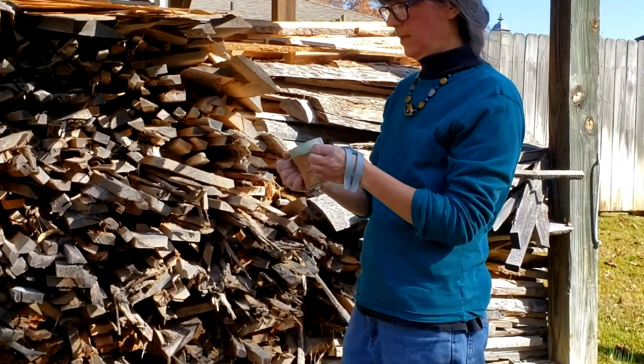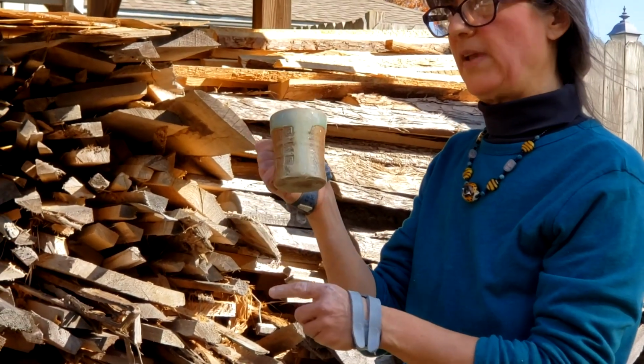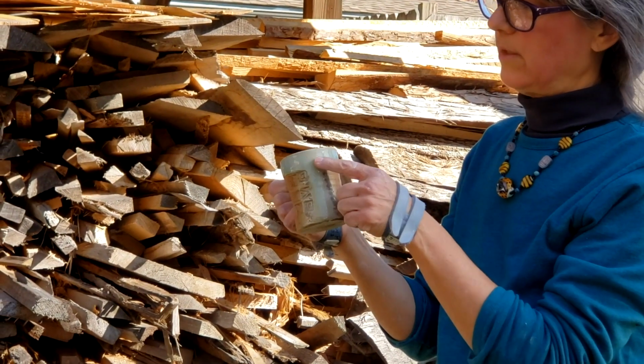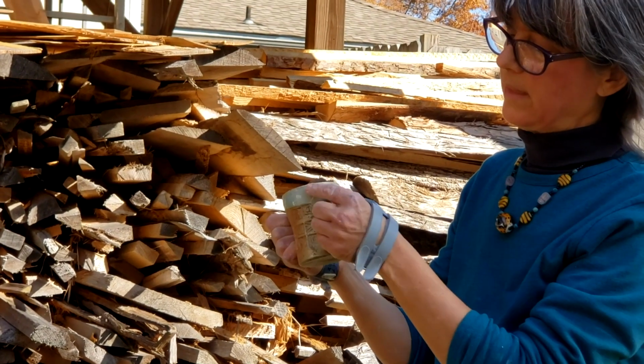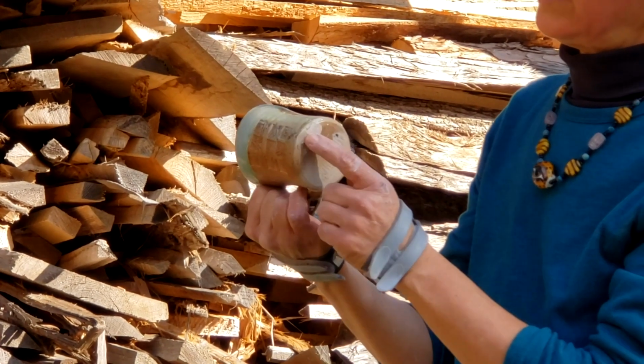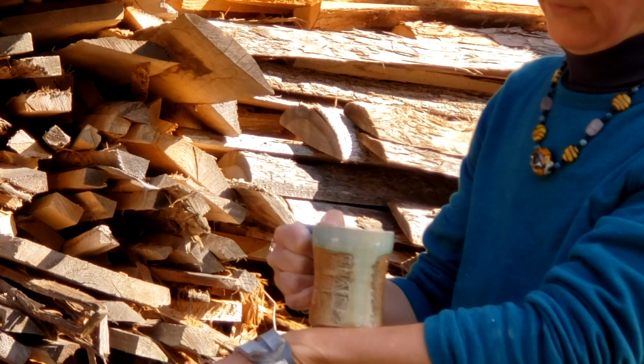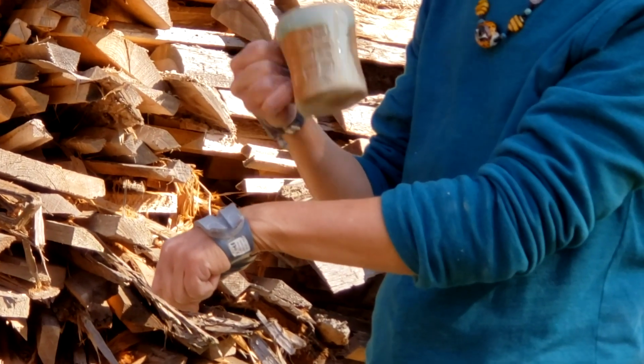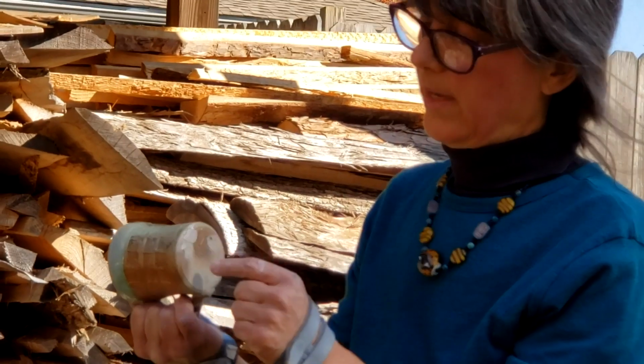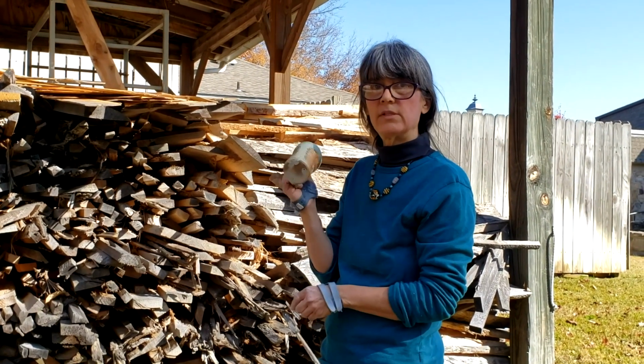This cup was put in the kiln facing the fire. So this front part was facing towards the fire. The glaze that's right here, I only glazed it to here. Once the wood ash hit it, it made the glaze melt or flux, and it ran all the way down the bottom here until it hit, it was going to go off the edge. If I had that right on the kiln shelf, it would have stuck on the kiln shelf and cracked the pot when we picked it up. But instead, it stuck to the wad, and we just ground it off. So we still have our cup.